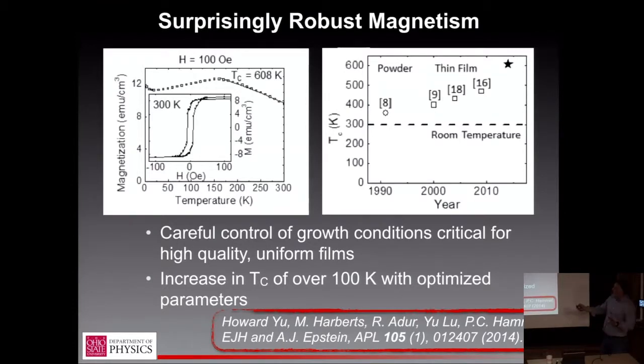For various reasons, it's tough to get a clean Bloch law fit to this, but at 300 Kelvin, it still has 85% of its maximum magnetization, and a linear extrapolation would give you an even higher temperature. But whether it's 550 or 600 or whatever, it's a very high ordering temperature. And the hysteresis at room temperature is quite nice. It's got sharp switching, a nice open loop.